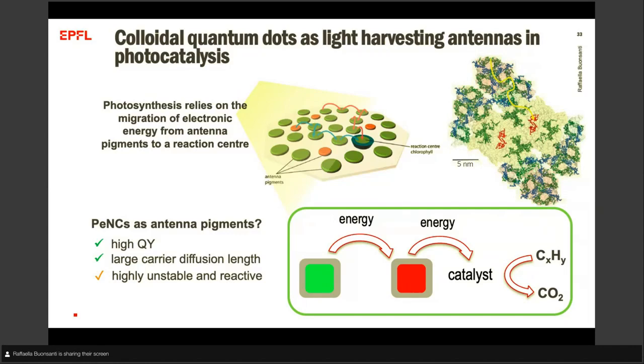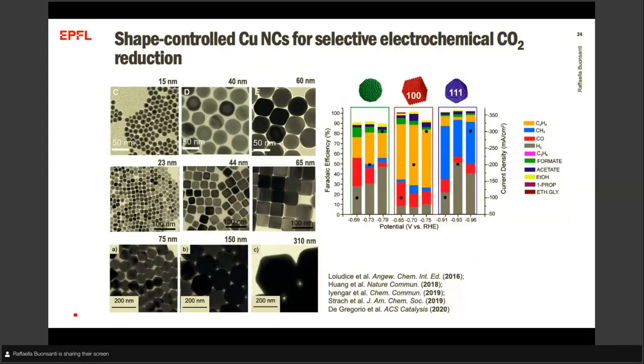And so the idea is now to combine this work more related to light-material interaction with our work on electrocatalysis, where copper is one of the main catalysts for converting CO2. We are doing quite substantial work on controlling the copper size and shape, because what we find is that the copper size and shape determines which product we obtain for the conversion of CO2. So for example, we obtain ethylene from CO2 if we use nanocubes, and we obtain methane if we use nano-octahedra, and a mixed product distribution if we use spheres. So now we are curious to see if we can drive this conversion directly with light, or maybe if light is also going to impact the reaction mechanism and therefore the selectivity that we find with these copper-based nanocrystals.